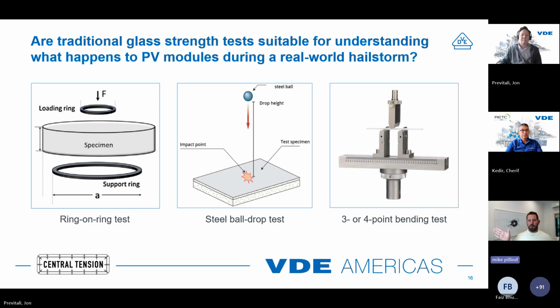On the full right-hand side, you have a 3-point bend test or a 4-point bend test in other formats. And what that fundamentally is doing as you push it down, those grinding edges that I talked about on the edge of the glass, those are flaws in the surface, on the edge of the glass, which act as origins for glass breakage. So when you do a bending mode, you're primarily looking at edge condition for 3 to 4 point bend testing. Ring on ring testing, you're doing surface stress.